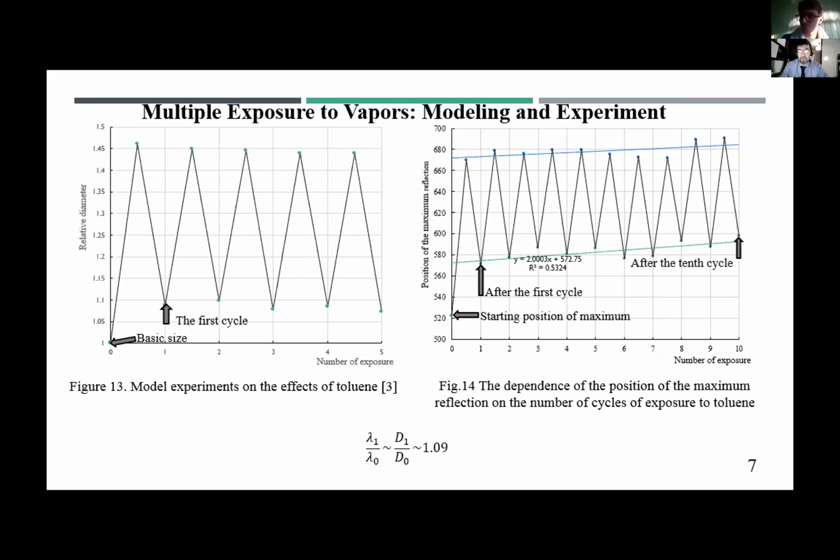With an increase of the dose of substance acting on a photonic crystal, irreversible changes can occur in the latter, which are expressed as degradation of the reflected signal from its surface. The absence of spectrally selective reflection from the surface of the photonic crystal has been observed due to the chosen dosage of the applied analyte. Such image blurs may indicate friability of the microsphere surface after treatment.